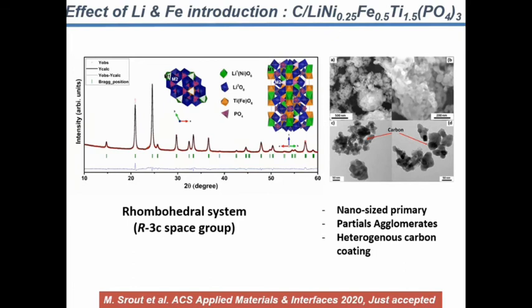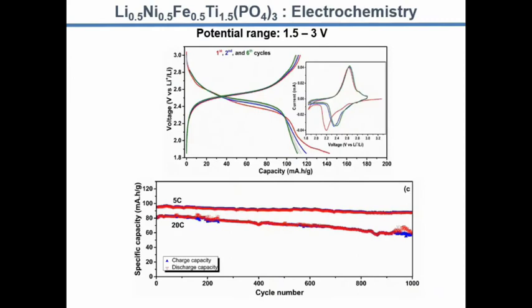From SEM or TEM, we can clearly see that we have nano-sized primary particles but with heterogeneous carbon coating. We don't have a very homogeneous carbon coating, which should be optimized in the future. So from electrochemical cycling, we can see that when cycling between 1.5 to 3 volt, during discharge we have a plateau at 2.5 volt, a reversible plateau, and CV also confirmed the reversibility of the insertion and extraction.